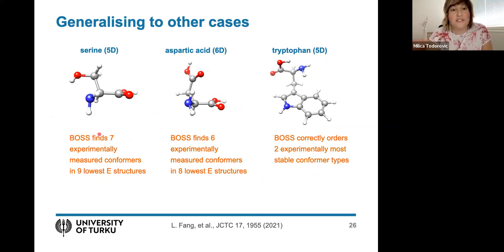And we found that for serine, all the seven experimentally measured conformers were found in the nine lowest energy structures. And similarly for aspartic acid, they had measured six experimental conformers, and we found these in the eight lowest energy structures. And in tryptophan, there were several hydrogen bonding types, and there were two that were experimentally confirmed to be lowest energy, and these are the ones we found as well.